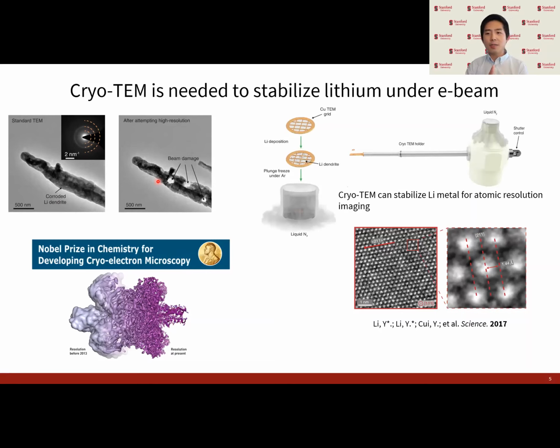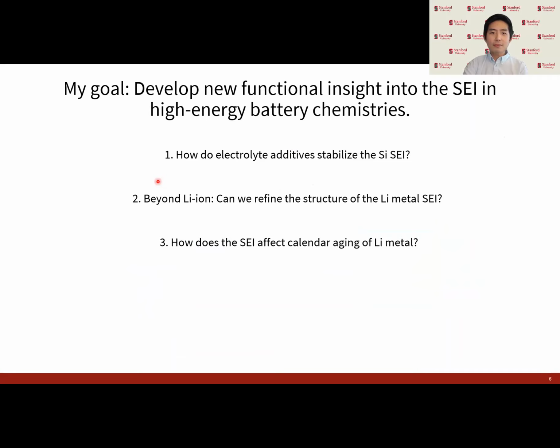And using this technique, our group was able to stabilize and image the lithium metal along with its atomic lattice. And now, using this technique, we can image and preserve battery materials and their SEIs with high resolution. So the goal of my PhD has been to develop new insight and understanding into the SEI of various systems. Here we'll talk about my work looking into the role of electrolyte additives in stabilizing the silicon SEI. Then looking beyond lithium ion chemistries, how can we refine the structure of the SEI on lithium metal? And finally, how does the SEI on lithium affect its calendar aging stability?